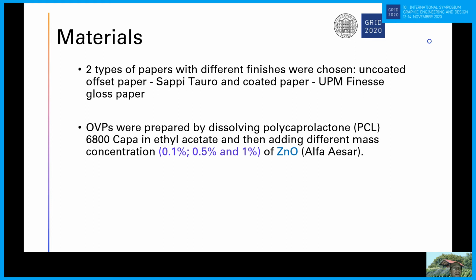The material, as said, we chose was polycaprolactone, which is a biopolymer and could therefore be biodegradable. We dissolved it in ethyl acetate, and afterwards we added different mass concentrations of zinc oxide. The mass concentrations used in this research were 0.1, 0.5, and 1%.